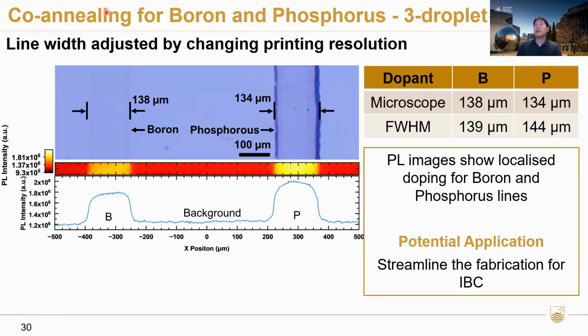So next, we try to apply this technology to co-anneal both boron and phosphorus, noting that both of them have an optimum annealing temperature of 950 degrees. We've also adjusted the number of droplets to intentionally make the lines a bit wider. This allows us to get closer to typical polysilicon lines in IBC solar cells. If we just look at the PL image, we see nice localized passivation around the boron lines and also on the phosphorus lines.